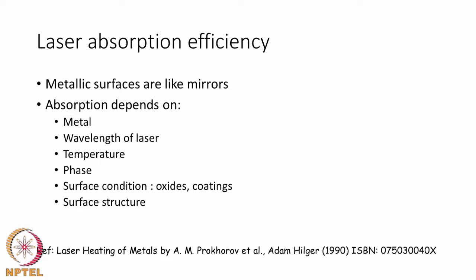The absorptivity is directly proportional to the frequency of the light that is being sent, or in other words inversely proportional to the wavelength of the laser, which means that between Nd:YAG which has a wavelength of about 1.06 micrometers and, for example, carbon dioxide which has a wavelength of 10.6 micrometer, you can see that the absorptivity with Nd:YAG is better than with respect to the CO2 laser. So, wavelength of the laser is also very important. Shorter the wavelength, the better is the absorption on the metallic surface.